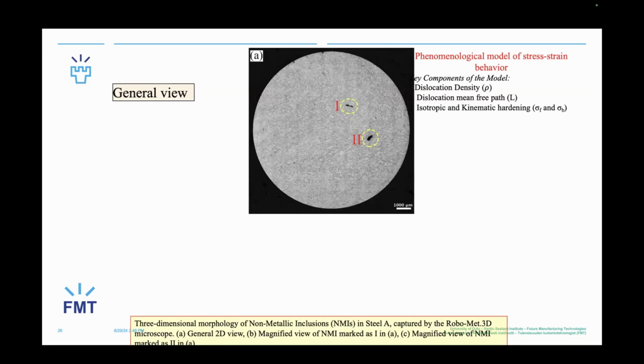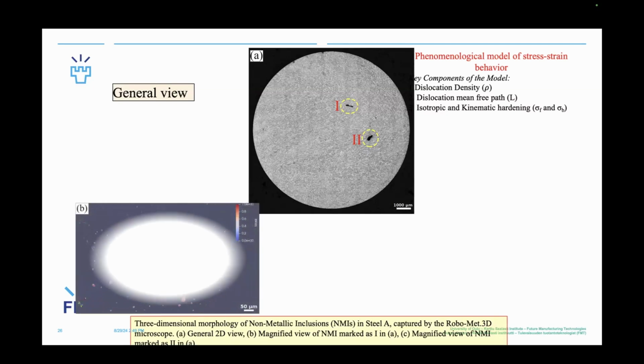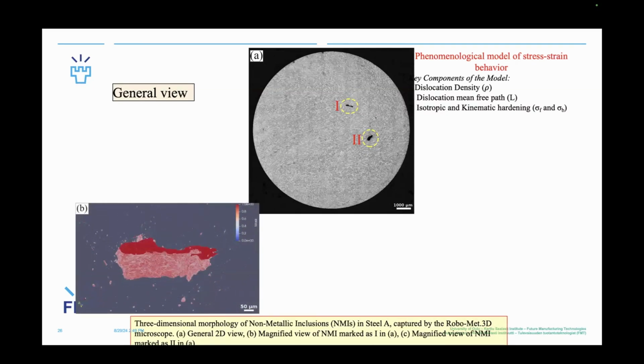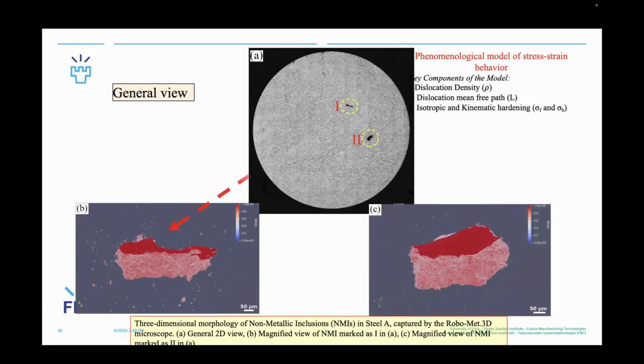This is the result of Robo-Met.3D. This Robo-Met.3D is a general view of steel A, a general map at low magnification, and we found here inclusion I and inclusion II. After 3D reconstruction from 72 sections, this is the shape and dimension of the non-metallic inclusion in steel A. You can see this big inclusion is the main reason for fatigue crack initiation, using Robo-Met.3D Pro.